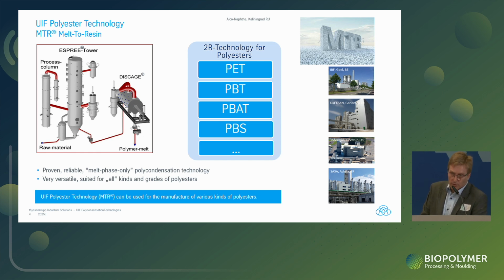With this melt-to-resin process, which depends basically on two reactors, an esterification reactor, which we call the ESPREE tower, and a final polycondensation reactor, which we call DISCAGE, we could establish that polyesters could be produced with the finally required molecular weight directly in the melt phase. This was a great success, and we established this not only for PET, but this process was also used for PBT, PBAT, and we think it can be used very well for the production of PBS in the future.